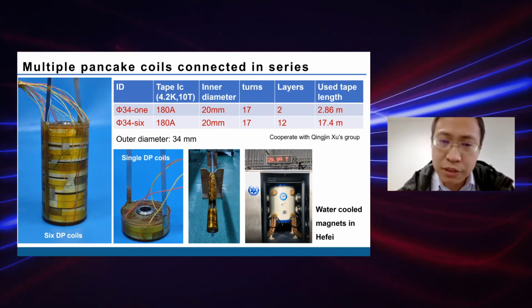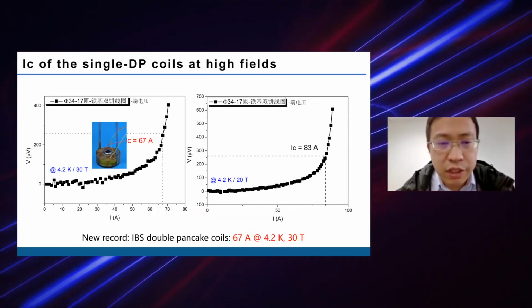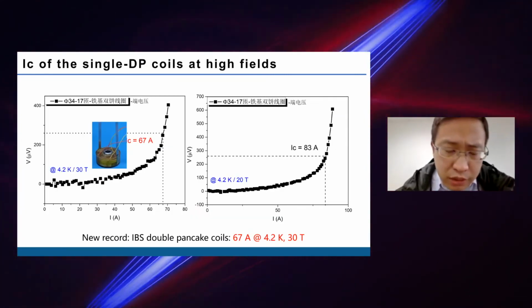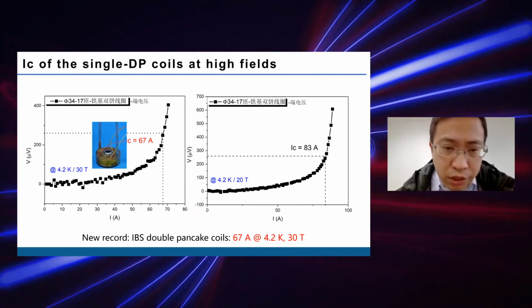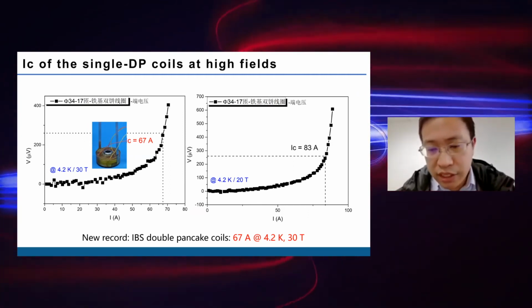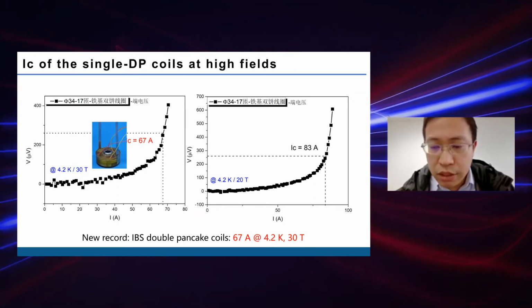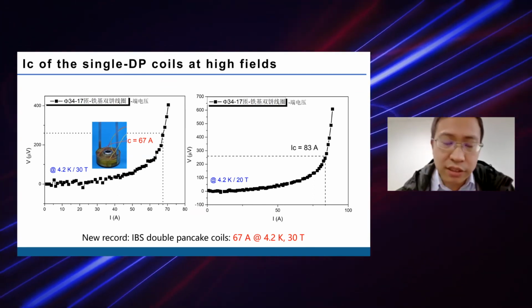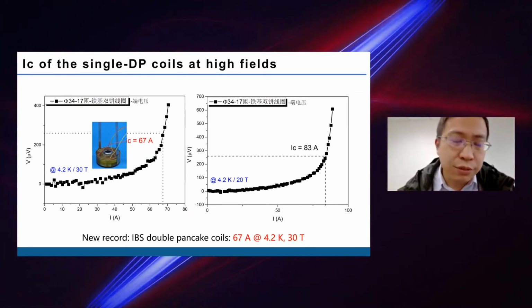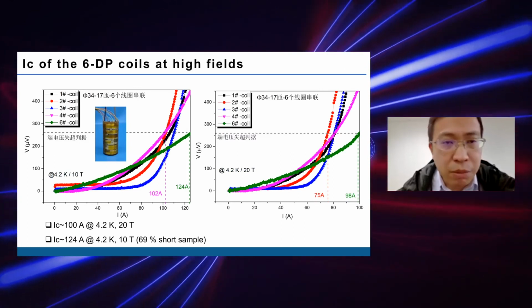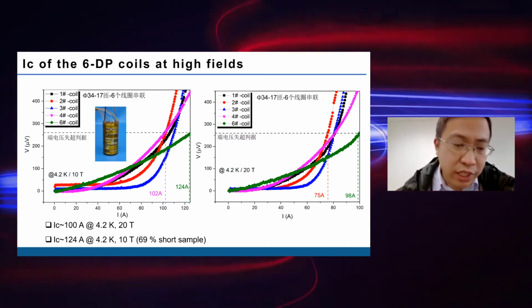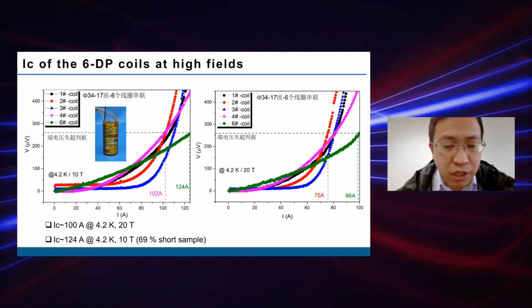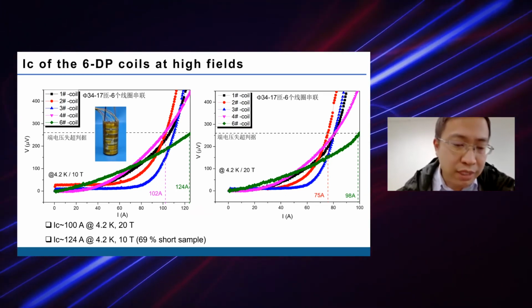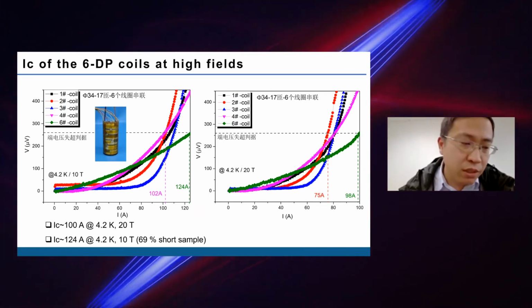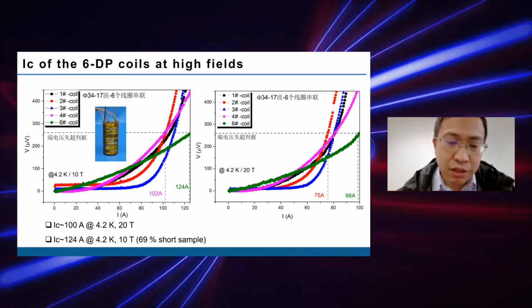at high fields. Now here are the results. For the single double pancake coils, we get 67 ampere at 30 Tesla. This is a new record. And for the 6 double pancake coils, we can get 124 ampere at 4.2 Kelvin and 10 Tesla, which is about 69% of the short sample.